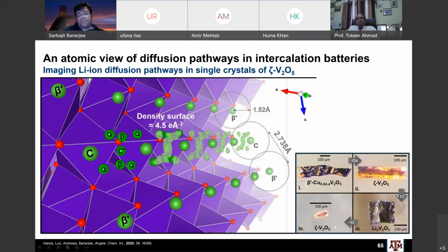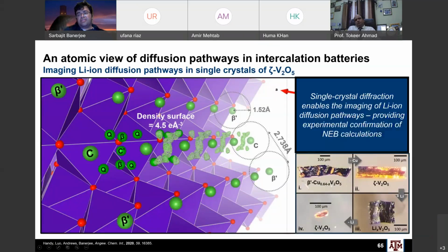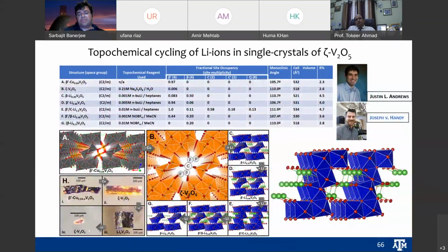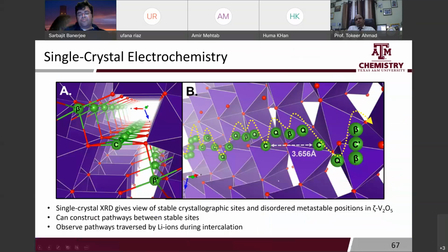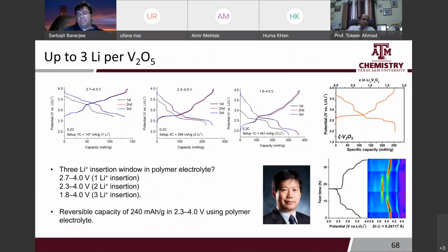and we can grow large single crystals of this. And this is actually some very new work that's just appeared and it's pretty unique because we are able to map the atomic diffusion pathways of ions through this using single crystal diffraction. So this actually gives us a very powerful means of looking at the ion diffusion pathways in this lattice, right? So providing us with experimental direct evidence of the sequence in which these sites are occupied in this lattice. Okay, and in terms of the results, of course, it's great to see that this is a very reversible material. We can get up to 440 milliamp hour per gram in zeta V2O5, making use of polymer electrolyte. That's what makes it stable.